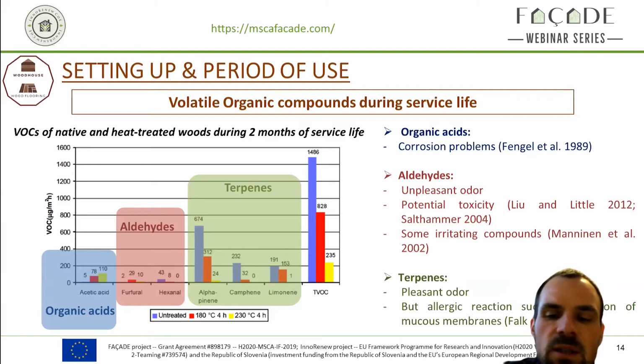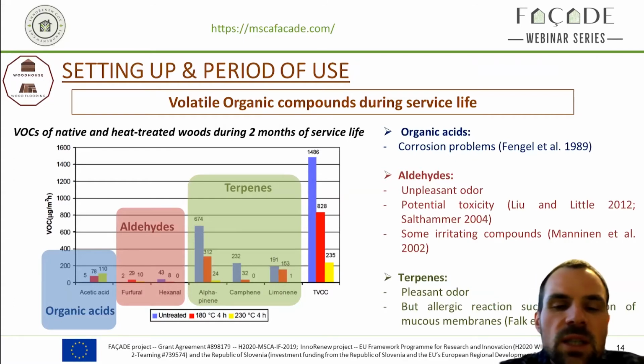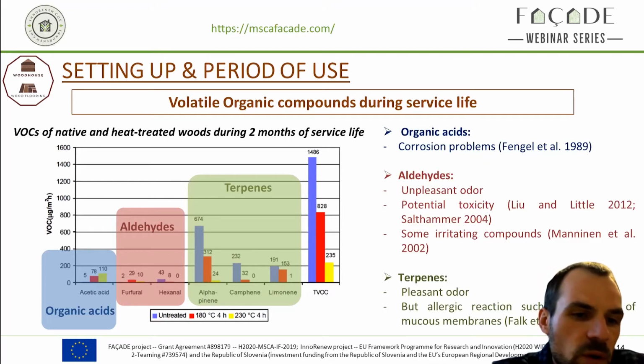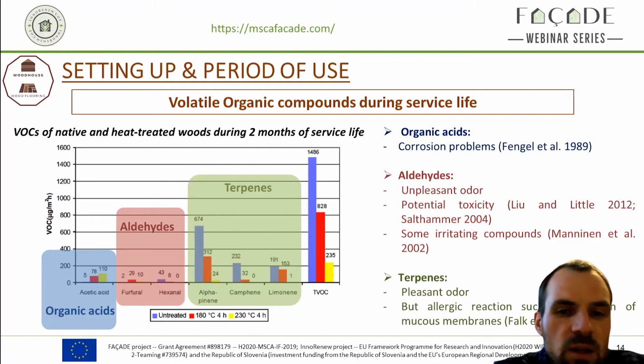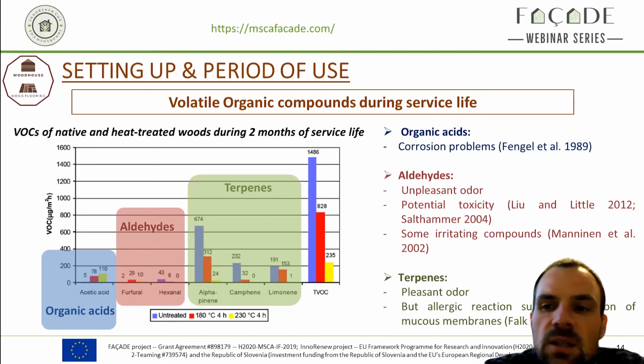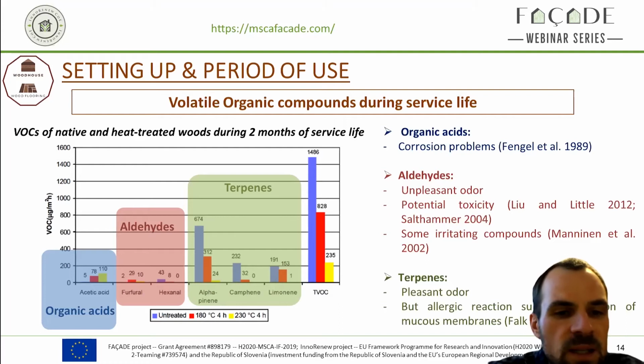According to this statement, it appears that heat-treated wood emits lower VOC content than native wood during its service life. In addition, we can see for organic acid, aldehyde, and terpene compounds, as well as for global volatile organic compounds, that the more severe the intensity of treatment is, the less VOC content will be emitted from the modified wood during the service life of the products.